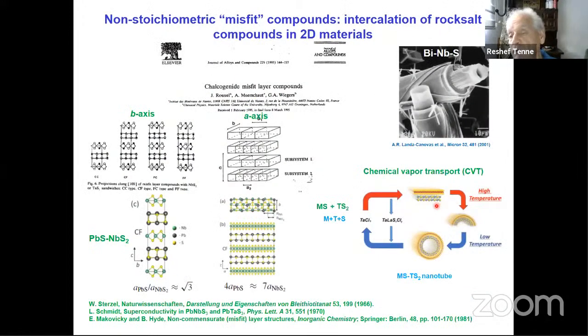Let me go to the last part of my talk, and this will be on misfit compounds, 2D misfit compounds. These are extremely interesting and nice materials. Again, layered compounds which are made of pairs of hexagonal materials like tantalum disulfide or niobium disulfide, and rock salt structures like PbS or lanthanum sulfide. These structures are typical 2D materials but they come in pairs. There is usually a charge transfer from the rock salt to the hexagonal sheet, and this charge transfer stabilizes the 2D structure, a pair of 2D materials that form together.